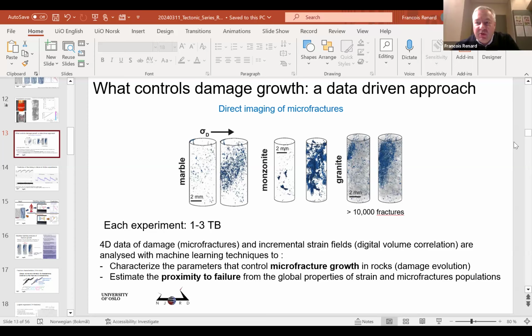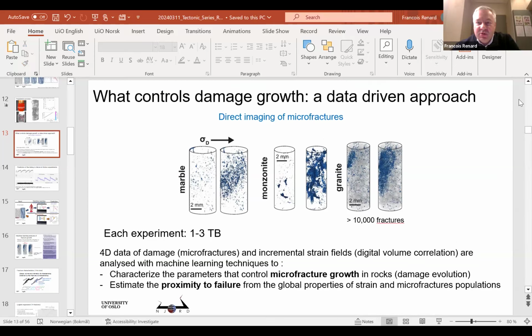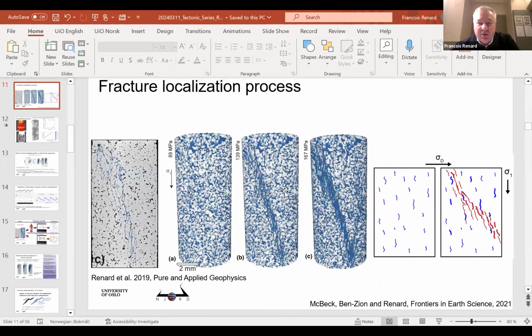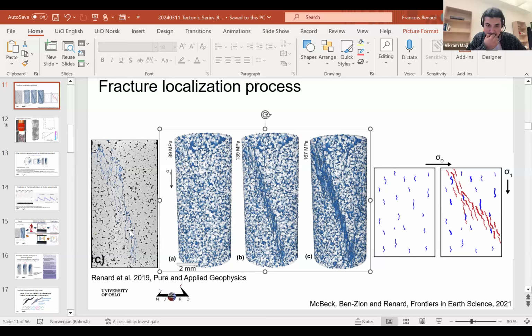So then you face the difficulty we have in high porosity rock. So I will show you a high porosity rock. This one is the high porosity rock. So all the blue is the porosity. That's a sandstone, 15% porosity. And in the porosity, some fractures develop. And the question is, can we separate the fractures from the pores? In this case, we were lucky because they have a different grayscale, so we could do it.